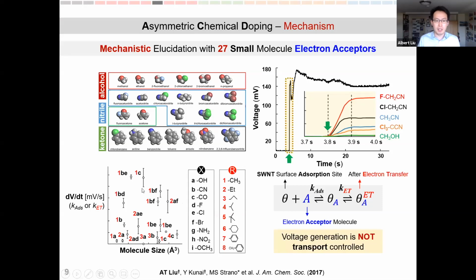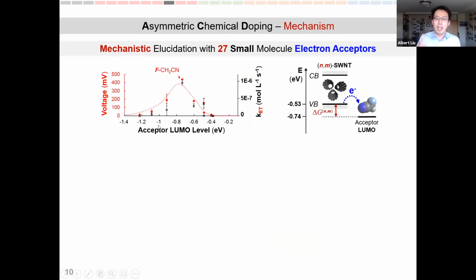If you plot this dV/dt slope as a function of molecular size, what we see is that there's absolutely no trend in between all of these 27 molecules. So this is a good indicator that this process is potentially not transport controlled. So then we ask the question whether this process could be electron transfer controlled. We plot the same data of the voltage build-up slope as a function not of the molecular size, but in turn as a function of the acceptor LUMO level.